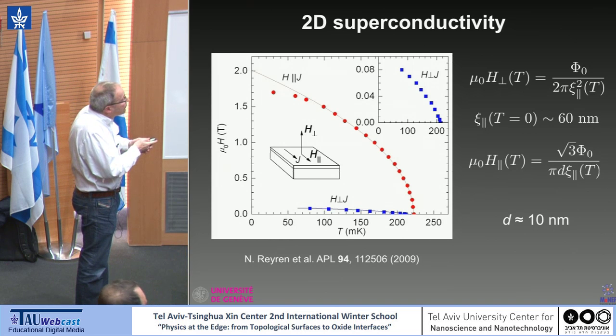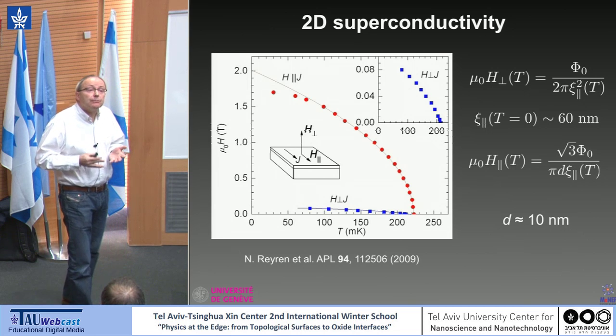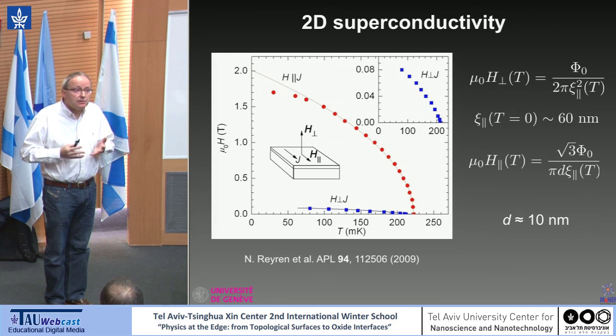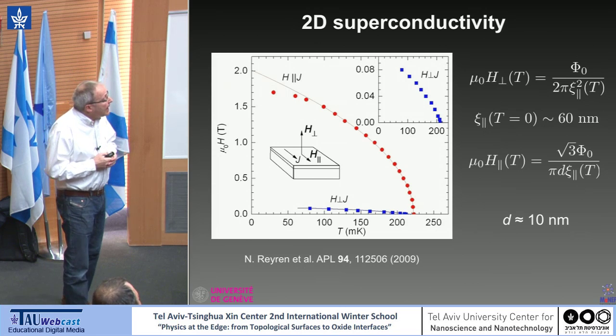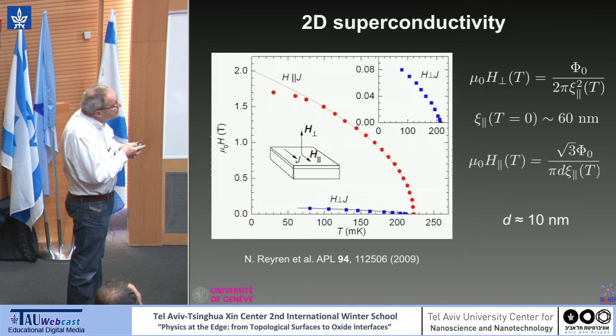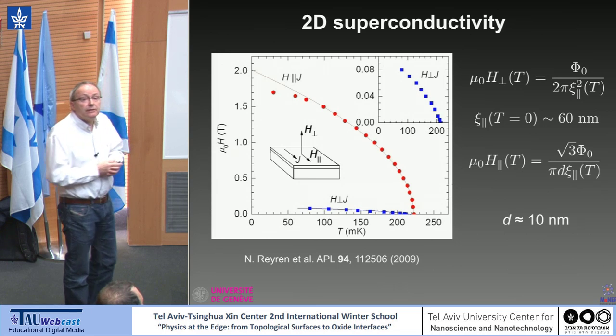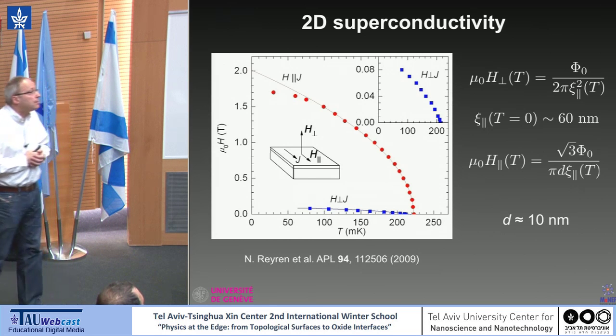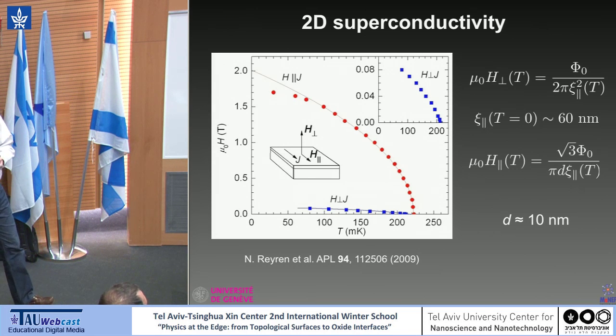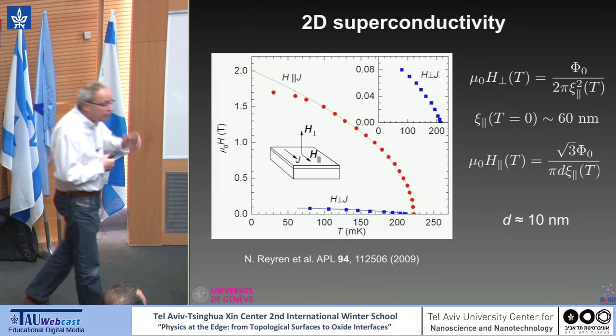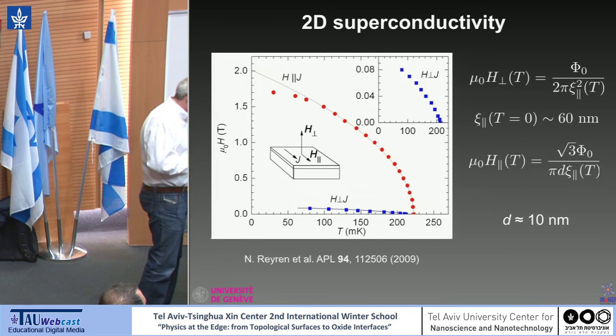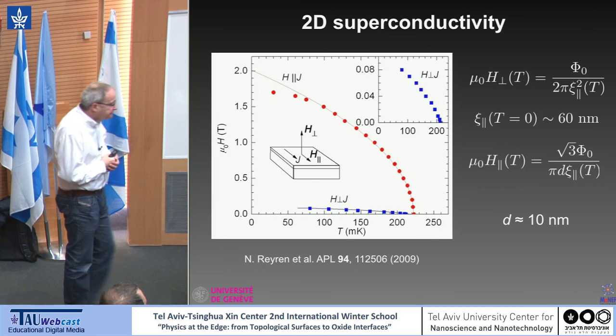And now for the specialist, when you see the square root of T behavior, you know that you're measuring a thin layer. This is a signature of a thin layer. And from this formula, which relates the parallel critical field to the in-plane coherence length that you know from the analysis of this curve, you can extract the thickness of the superconducting layer, again, about 10 nanometer. And I will use this technique a little later, and I will explain why.